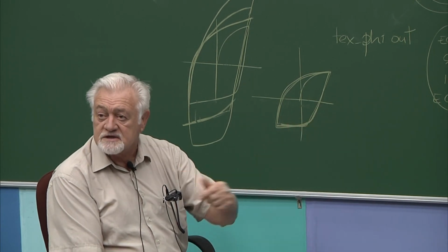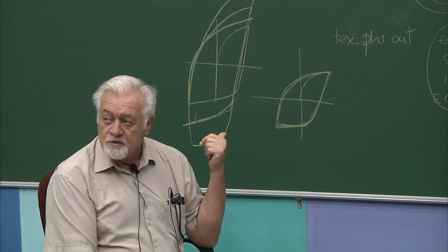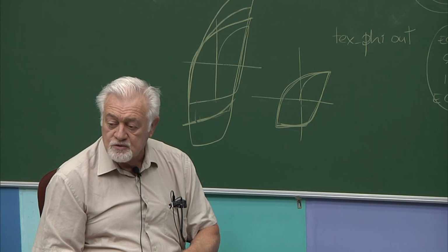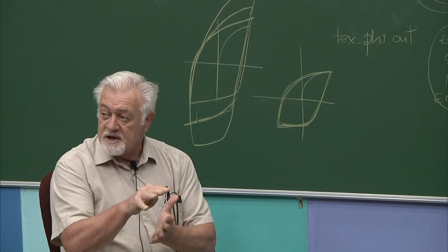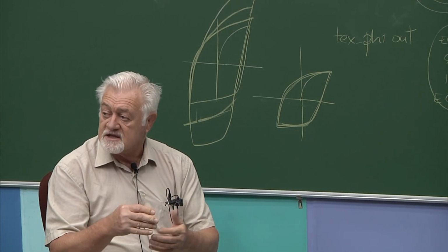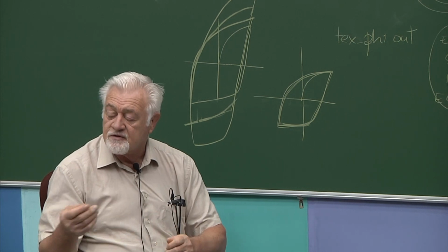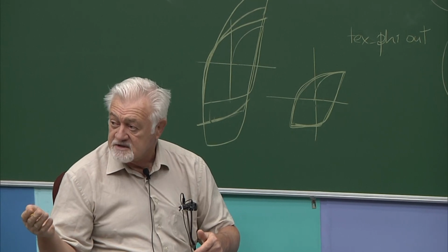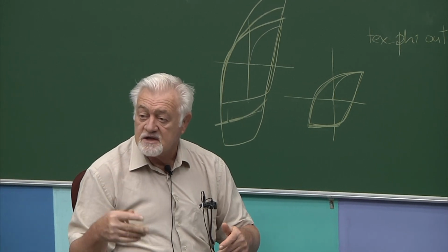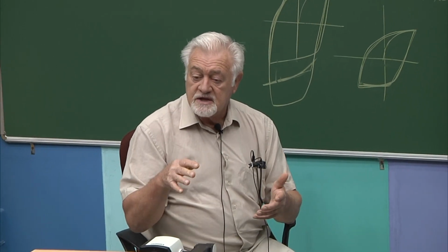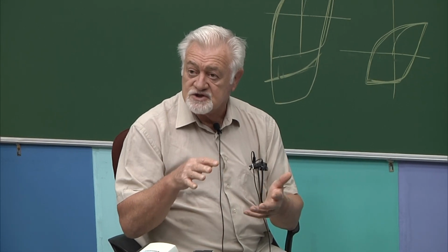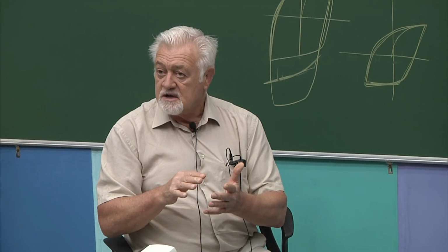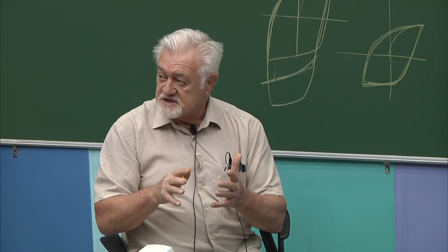But then when we started looking at the shear results, we realized that we needed a mechanism, which is we had to exclude the coplanar slip from hardening the material, from contributing to the reversibility parameter. On the contrary, the reversibility parameter was not changed if we have coplanar slip, and that is because in shear you don't activate a lot of systems.